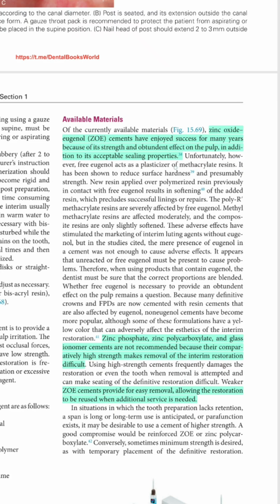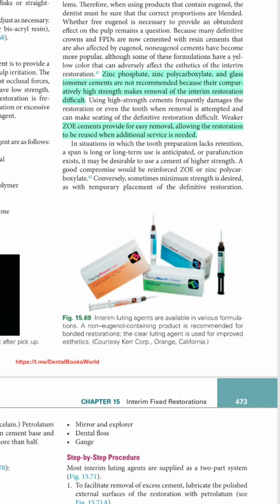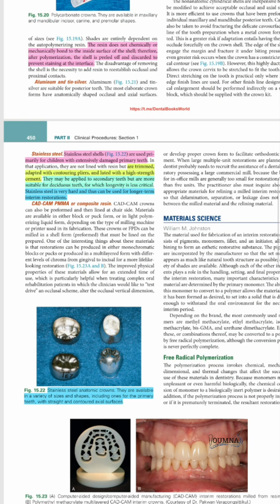Zinc oxide eugenol is the most used interim cement, and it has shown success for many years due to its strength and its favorable pulp effect, in addition to its acceptable sealing properties. We should not use zinc phosphate, zinc polycarboxylate or glass ionomer as interim cements, because they have high strength that makes removal difficult, but ZOE cement is easily removed, and it allows the restoration to be reused when additional service is needed. But when we are using stainless steel shells as a long-term interim restoration for the deciduous teeth, we use a long-term luting agent like zinc phosphate, polycarboxylate or glass ionomer.